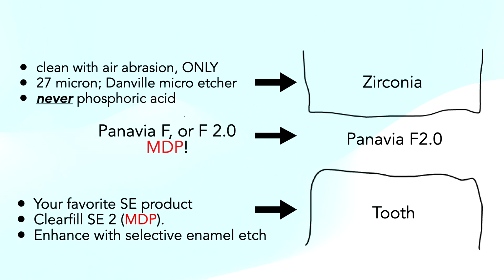Now, on the trade journals, how do they advertise cements and luting agents? They never talk about the physical properties of bond strength. What do they tell you? It's easy to clean up, right? Well, if it's easy to clean off the outside, is it sticking to the inside? There's no adhesive value to it, okay? So that's the fly in the ointment: you're going to do a little work cleaning the extra Panavia off the outside because it's going to stick. And a tip, I always use some Vaseline on the outside of the zirconia on the proximal contact areas to make it a little bit easier to clean up, okay?